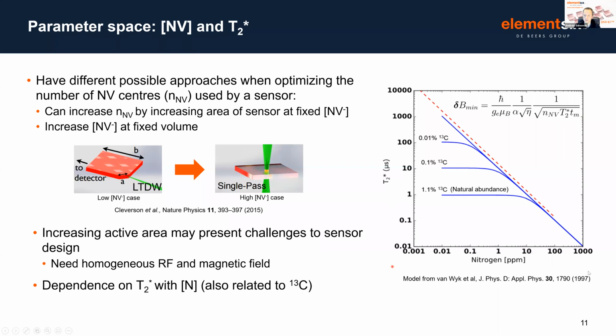And this is the plot that has been lurking on the right-hand side of this slide. This shows the dependence between nitrogen and the coherence time with different abundances of carbon-13. Now, we can use this to pick out areas of interest in terms of developing an NV containing diamond material. Now, in the single NV case for electronic grade or ELCVD, we obviously sit here in terms of nitrogen concentration.